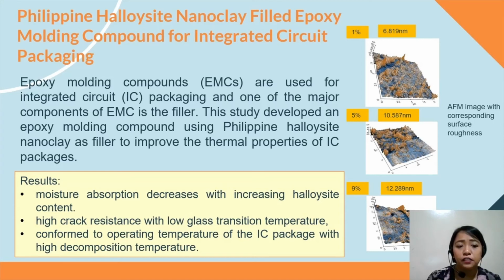So for the results, we observed that moisture absorption decreases with increasing halloysite content, and high crack resistance with low glass transition temperature was observed as well. So the product produced conformed to the operating temperature of the IC package with high decomposition temperature.